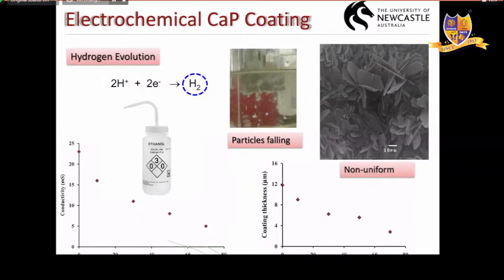Unlike in other materials like nickel plating or zinc plating, where the coatings are very adherent, in this case they are not adherent. It is falling down. Again, the hydrogen evolution reaction is playing a role there, which causes the coating to break and fall down.